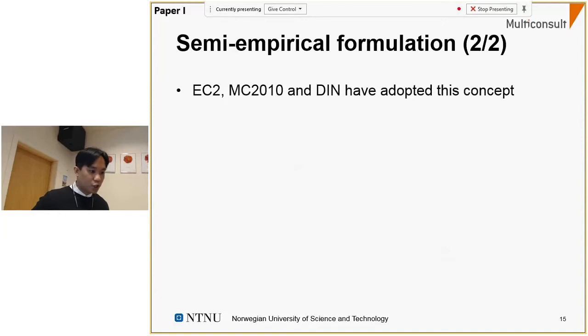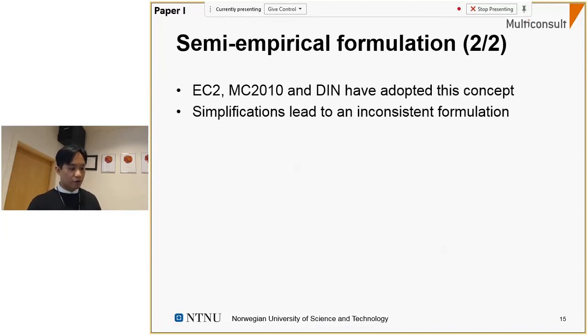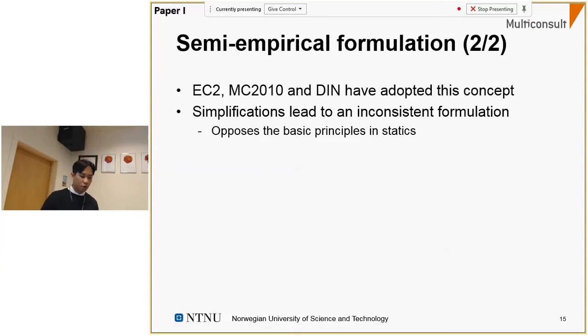Now, it can be shown that the Eurocode 2, the fib Model Code 2010 and the German Annex have adopted this concept. However, the simplification of not explicitly solving this differential equation leads to an inconsistent formulation, whereas the basic principles in statics are opposed. An example of that is that the equilibrium in calculating the maximum crack distance, for example, is violated, which from a structural engineering point of view is really not convincing at all.